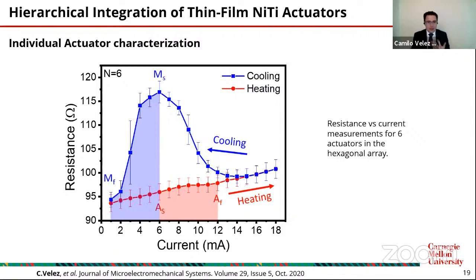So one of the tests that we found, based on the literature, was the resistance measurement. And this was very accurate and very insightful, because we generate these types of plots where you just change the current, and by changing the current, you are changing the temperature. And if you change the current back and you measure the resistance, you are also getting the hysteresis during the Martensite transformation. If you notice, it doesn't look like the other shape for the stress, but it's a good indication of the transition of the material.